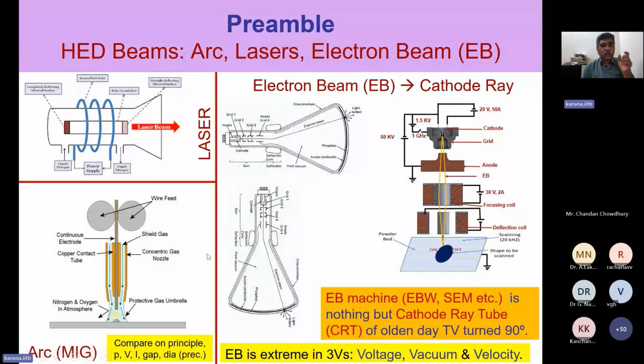Okay, based on this, we can compare other things. For example, pressure. You need always ionization to take place. For ionization, you need an environment. So you need gas. So the pressure of the gas is about 1 atmosphere or a little more because argon will come with some force. So at the arc, the pressure is slightly more than atmospheric. Okay. And the gap between the electrodes is hardly 10 millimeter or 8 millimeter.